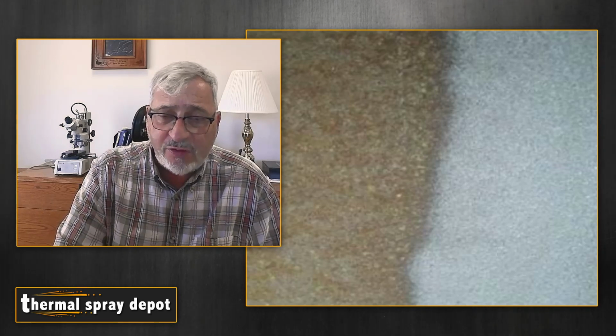This picture doesn't do it justice, but this has what we call a raised profile of 3,000ths to 5,000ths, and it's got thousands of small little nooks and crannies for two things to occur. First of all, the total surface area is increased tremendously, so you have more area for what are called van der Waals forces to help with the adhesion. And secondly, you've got a very clean, what we call activated surface, which involves the van der Waals forces, which gets into a topic that's much deeper than what these videos are aimed at. Now, if you use this grit blast surface on either the knurled or the threaded surfaces, that would be phenomenal. That would be your best case scenario, because you've increased the surface area and increased the places where the thermal spray can lock into it. And that's where you get your best results.